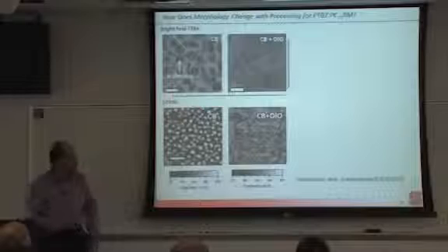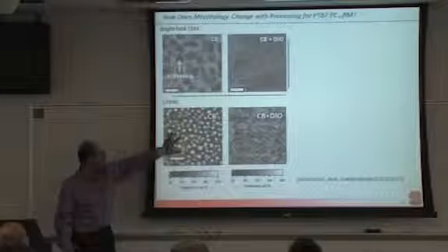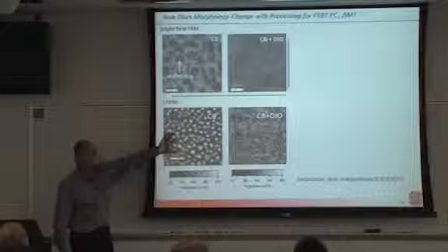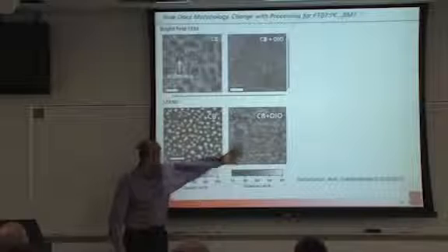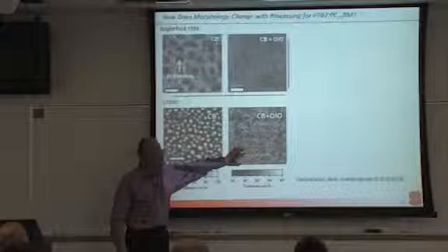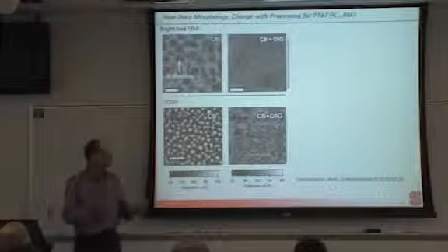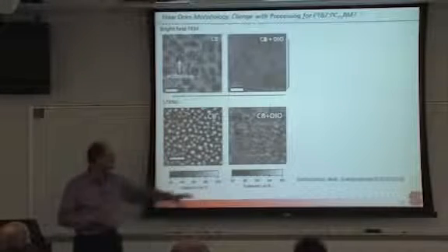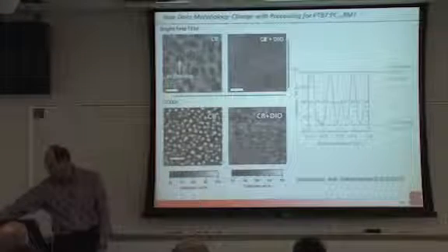All right, so if I do this now with X-rays, and the size scale has changed a little, I get very nice images for the domains that are large. I can do a quantitative composition map. I struggle in real space. I'm reaching the size limit that I can look at, and maybe I have a 2D projection of a 3D structure. So with DIO, the real space X-ray microscope also struggles.